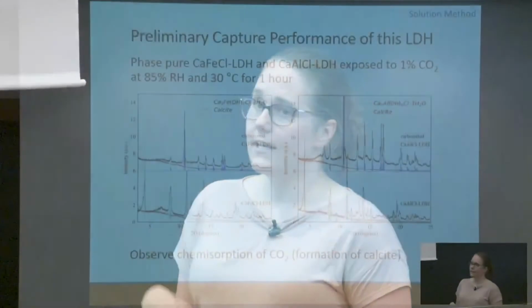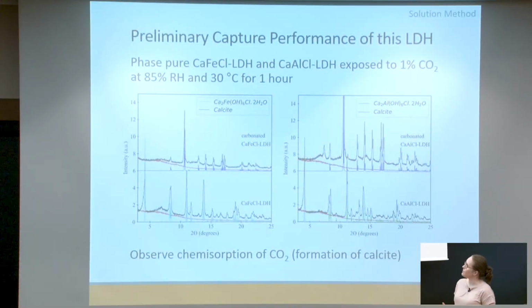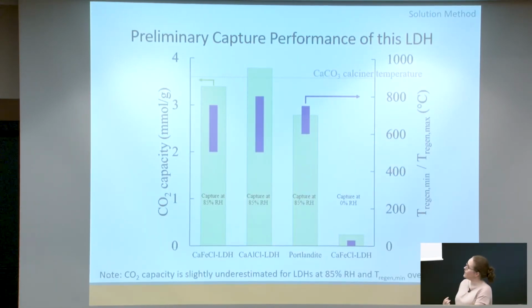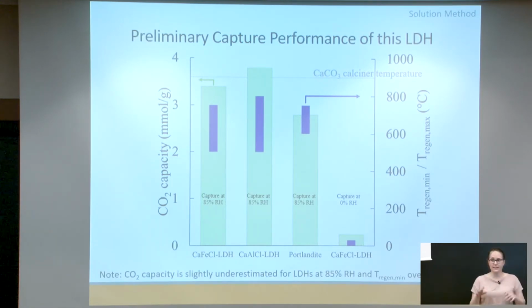So now let's look at the capture behavior of these layered double hydroxides. We expose them to 1% CO2, a relative humidity of about 85%, which is quite high, at room temperature for an hour. And what happens is you go from these pure LDHs and you actually form calcite. So this is chemisorption. This is strong CO2 sorption that's occurring. But if we change the relative humidity, so here is relative humidity of 85%, if we change it to 0%, then actually we get physisorption of CO2. So relative humidity is going to be very important, and this is something that we're now studying, trying to understand at what relative humidity we get that transition from physisorption to chemisorption.